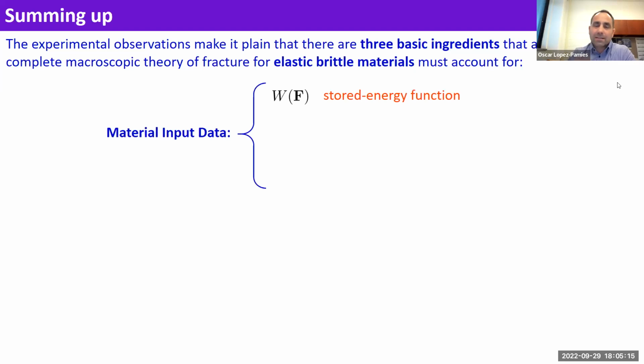Those are the elasticity. Let's say we're going to talk about elastic materials: the elasticity of the material, the strength surface of the material, and the so-called critical energy release rate, right? So this controls elasticity. It controls also the competition with nucleation and propagation of large cracks, and the strength controls nucleation in the bulk. So in addition to these basic ingredients, the theory that one has to develop has to account for an interpolation between strength and toughness. And so that's, again, just from experimental observation.